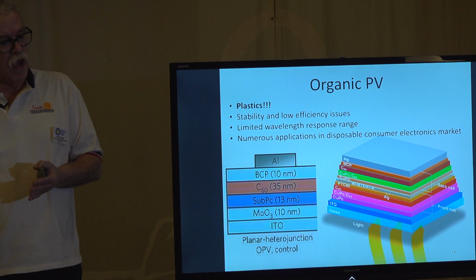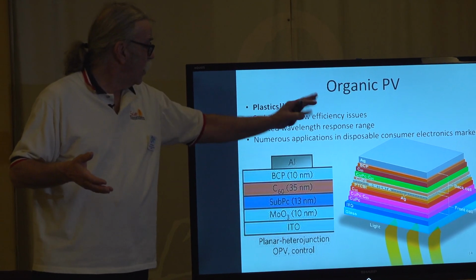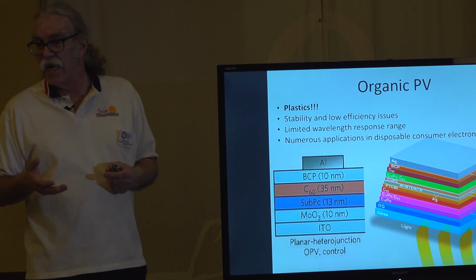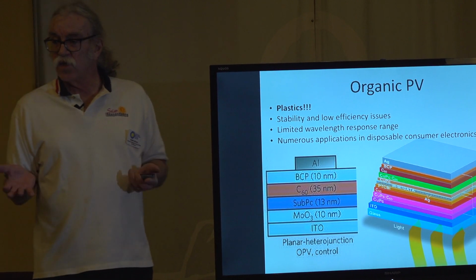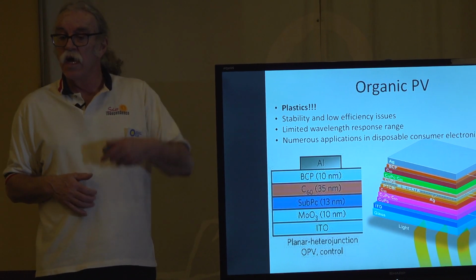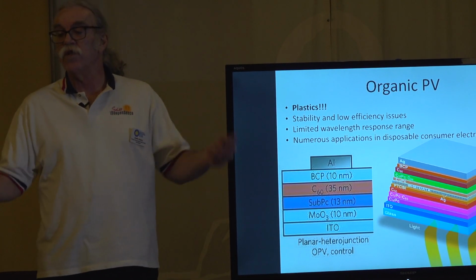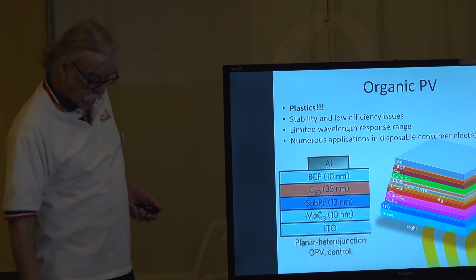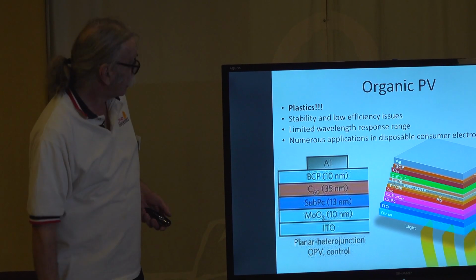But they all absorb basically in the visible, maybe the near infrared. Silicon goes out to 1 micron. The furthest out any of these go is about 800 or 900 nanometers. And that's a showstopper. It means they're not going to be as efficient. They're throwing away too much of the solar spectrum.